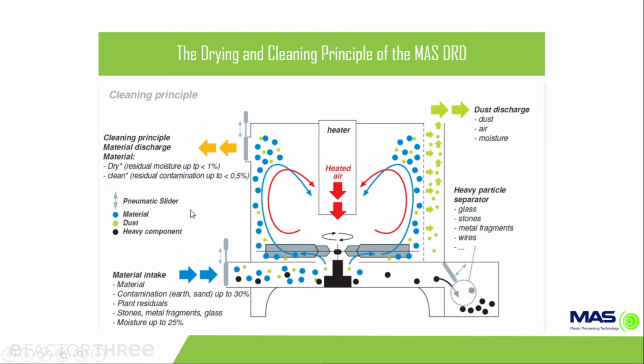And it dries through this process. It dries off the dirt on the surface of the flake, and then the actual friction among the particles liberates the dirt into the air, and there is a continuous suction on both sides of this machine. We're taking away the dust-laden, wet air and filtering it out. And once we reach a certain stable temperature, we have the material in there for another about 15 seconds, and that cleans the material to a very good degree. Now, this technology cannot remove any oily or greasy substances, so it's not designed for food packaging or things of that nature.